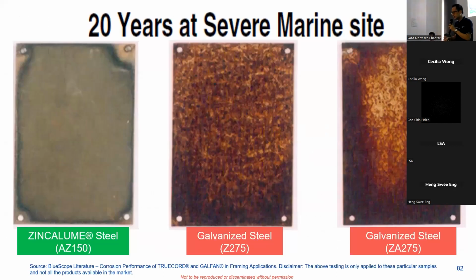And this is a 20-year exposure sample that we got from Australia. We can see that after 20 years it still performs with very limited corrosion activity as compared to the GI sample. Here we put a sample of GI Z275 and also another product family called Galfan ZA275. So all this product family is able to perform better as compared to the other product family, like single zinc steel in this case.